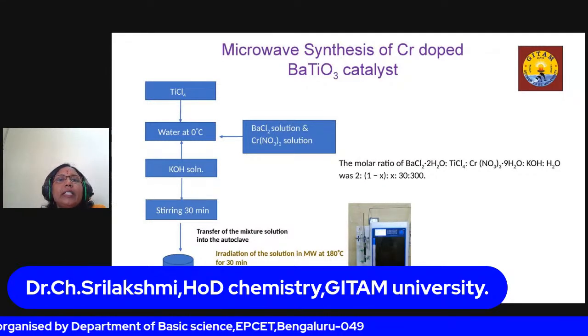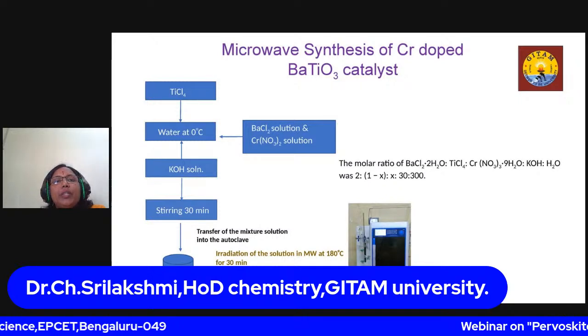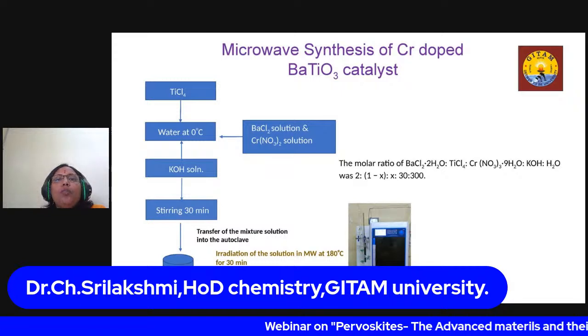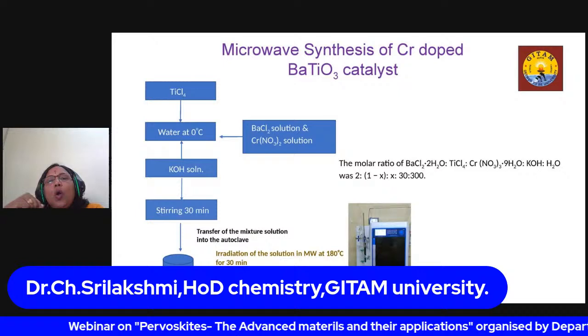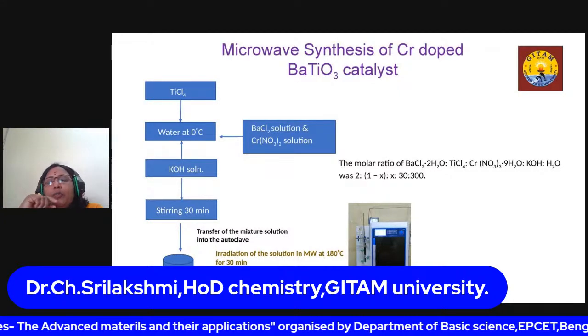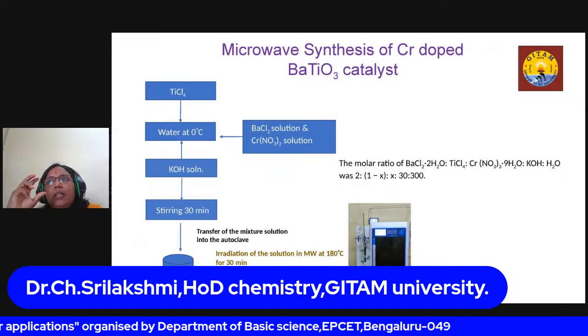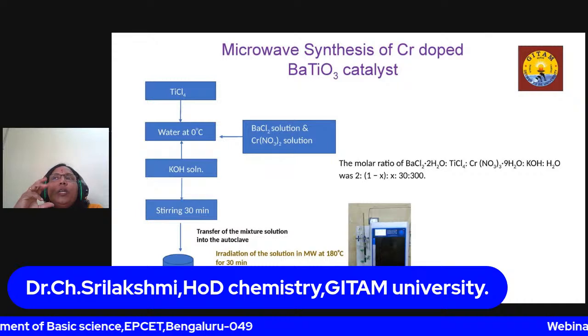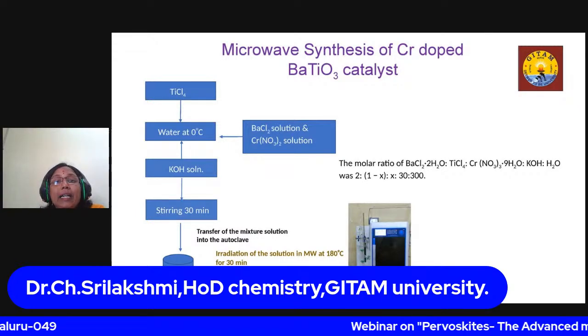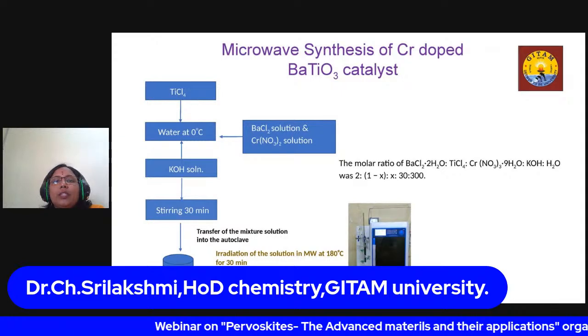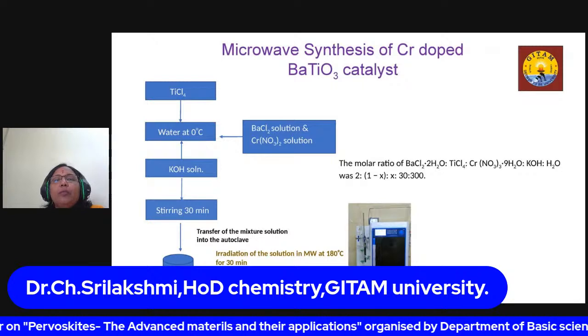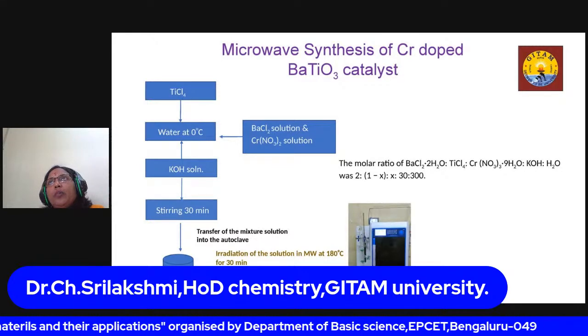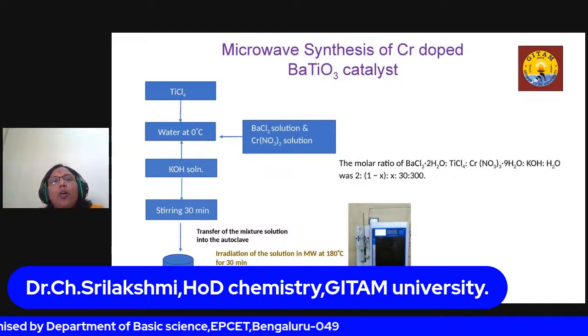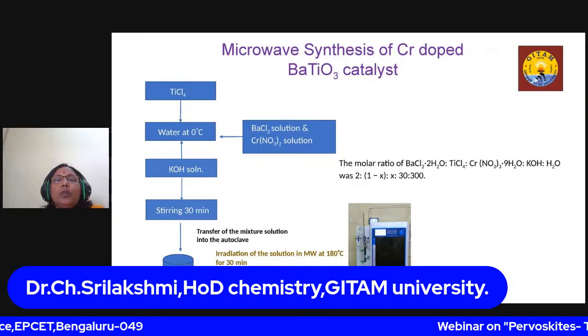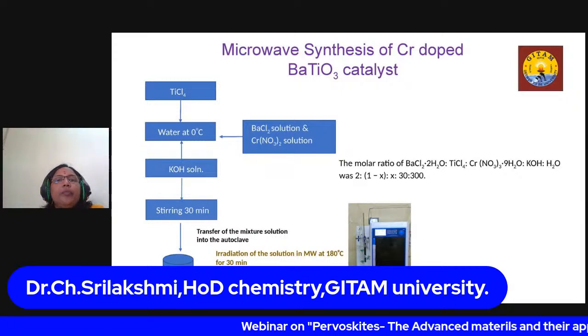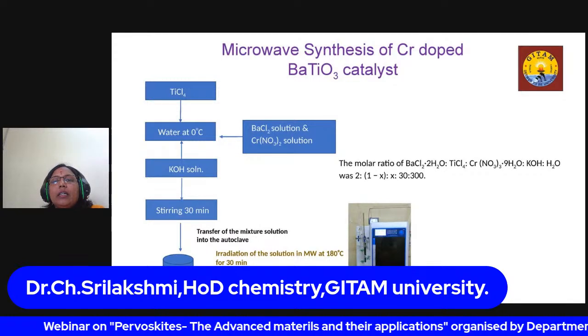So what are the raw materials? Titanium chloride, barium chloride, and chromium nitrate are used as precursors for the preparation of chromium doped barium titanate. In microwave synthesis you can't use whatever material you want, because the raw materials should be good microwave absorbents. Then only the required phase will be obtained. Here I cannot use chromium chloride because it is not available, so I have taken chromium nitrate and mixed it with barium chloride. Chloride precursors are good microwave absorbents. You can use all chloride precursors except one or two, so that heat will be transmitted nicely in the mixture. All these ingredients are mixed in the ratio mentioned here.